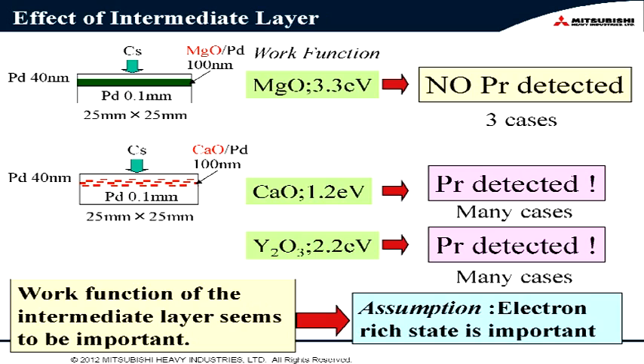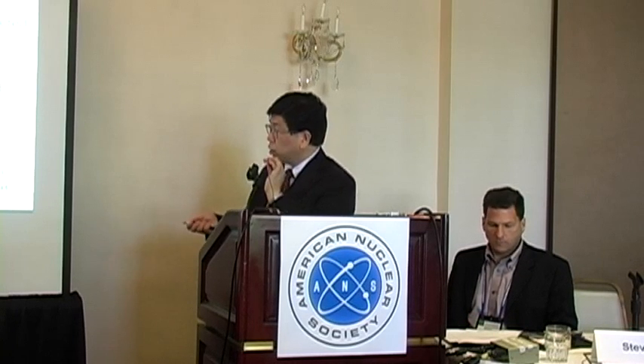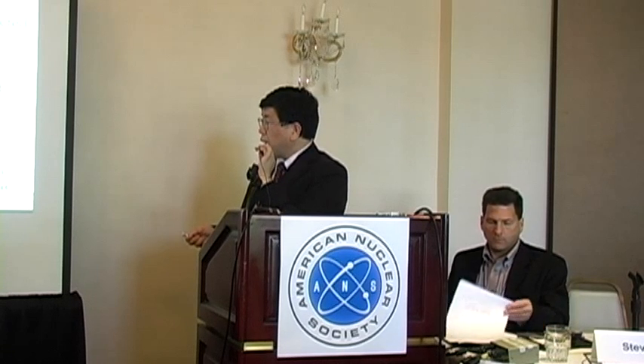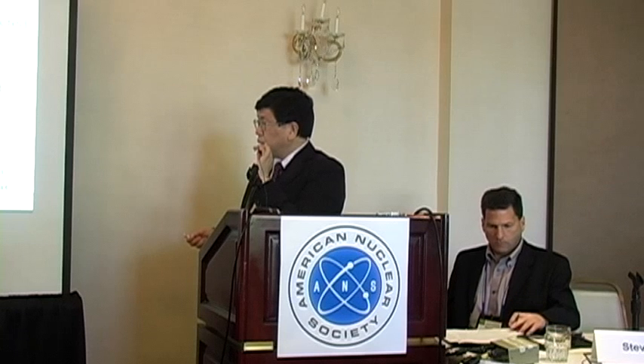And the work function of magnesium oxide is 3.3 electron volts, and calcium oxide has a very low work function, and Y2O3 also has a low work function. These materials emit electrons very easily. So the work function of the intermediate layer seems to be very important. If we have an intermediate layer that is a good electron emitter, we would have an electron-rich state on the surface of the palladium sample. So we now have the assumption that the electron-rich state is important.